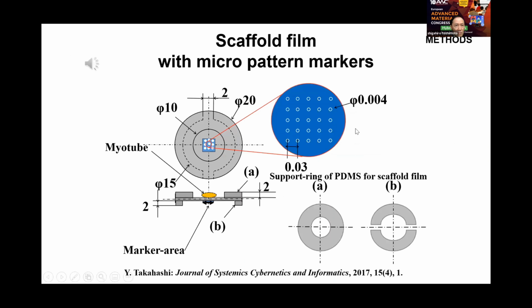The slide shows arrangement of markers. Micro-protrusions of hemisphere shape, diameter of 4 micrometers, are arranged on the rear side of the scaffold thin film of PDMS with interval of 30 micrometers. The thin film is sandwiched between cylindrical rim supporters of PDMS.